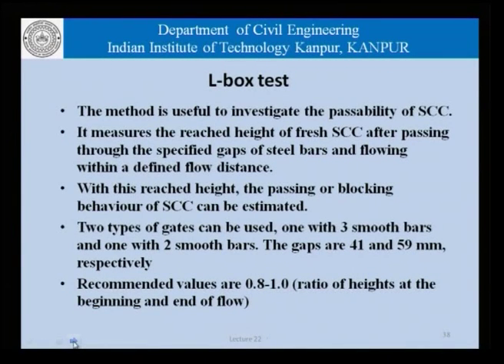As I explained before, this is what is given in the text here. The method is useful to investigate the passability of self-compacting concrete, the passability being the ability of the concrete to negotiate the simulated reinforcing bars, and it measures the reached height of fresh SCC after passing through the specified gaps of steel bars and flowing within a defined flow distance, which was shown to be about 700 millimeters in the previous slide. And with this height reached, the passing or blocking behavior of the self-compacting concrete can be estimated. And two types of gate can be used, one with three smooth bars or two smooth bars. The gaps would be different depending on the kind of diameters of the bars that we use and so on.